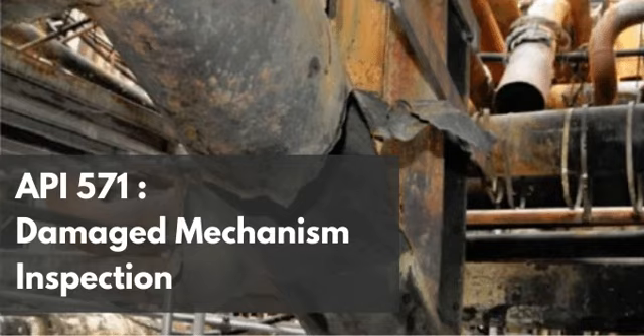It kind of sounds like a vinaigrette salad dressing that's been left sitting on the counter. That's precisely it. The oil and the vinegar separate. Right. But here is the major structural problem with that happening inside solid steel. Okay, what is it? As that chromium-rich alpha prime phase precipitates out, it doesn't just sit there harmlessly in the lattice. Right, it has physical volume. Exactly. These new microscopic structures act as literal roadblocks within the crystal lattice of the metal.